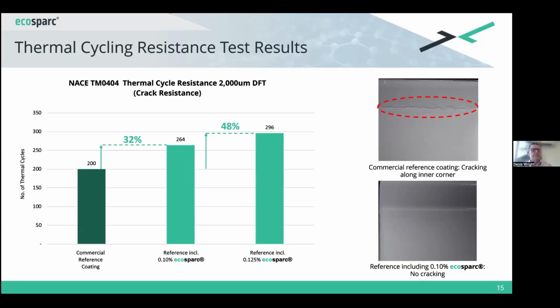The first round we did, right-hand side there, 252 cycles as per TM404, and we saw in a coating with graphene at the right percentage, no cracking and no graphene cracking. This test goes from -30 to 60 degrees, 252 times. So we thought, well, we haven't tested the graphene to failure, so let's do that. So we grabbed a commercial coating that was commercially made with graphene, with the ecosparc additive in it, and with that ecosparc additive, through that crack test, it lasted 32% longer to failure.